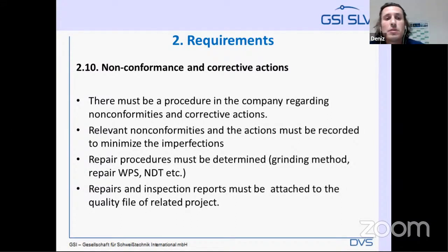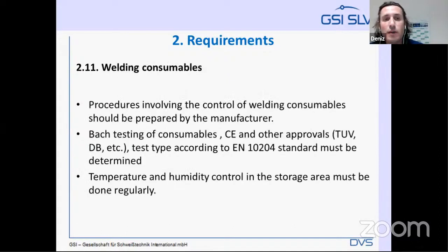Non-conformance and corrective actions. There must be a procedure at the company regarding non-conformities and corrective actions. Relevant non-conformities and actions must be recorded to minimize the imperfections. Repair procedures must be determined, for example, grinding methods, repair WPS, NDT, etc. Repair and inspection reports must be attached to the quality file of the related project. Welding consumables. Procedures involving the control of welding consumables should be prepared by the manufacturer. Batch testing of consumables, CE, and other approvals, for example, TÜV or DB, and test type according to the EN 10204 standard must be determined, and temperature and humidity control in the storage area must be done regularly.